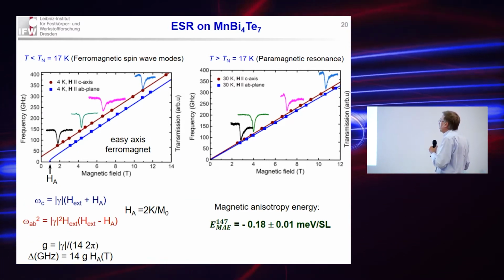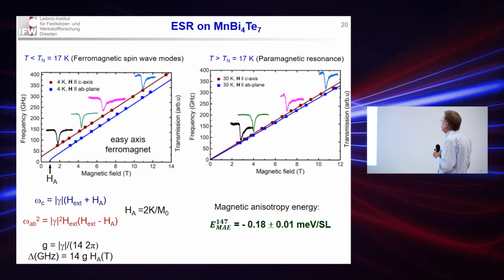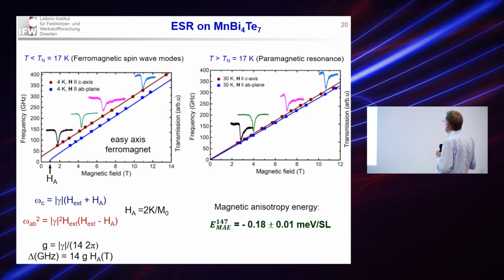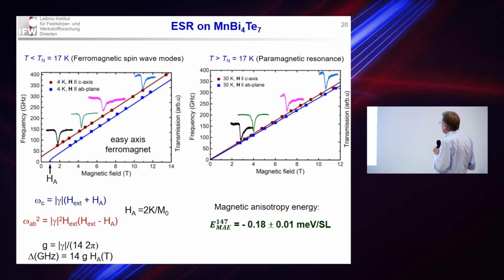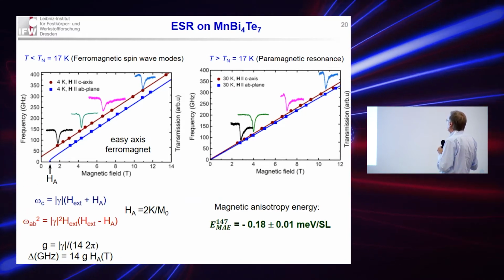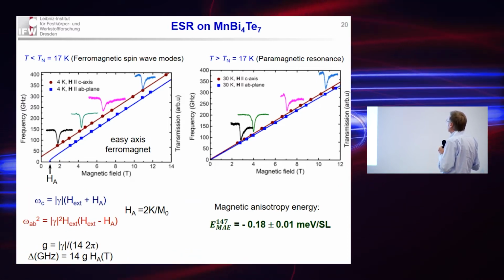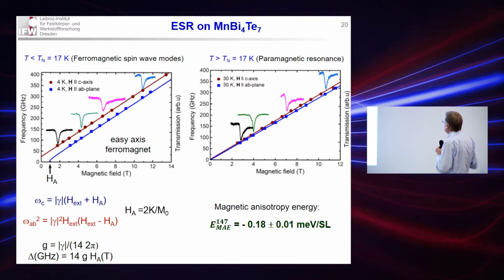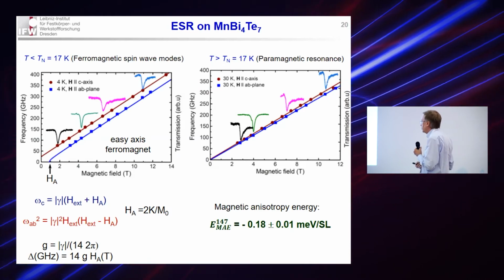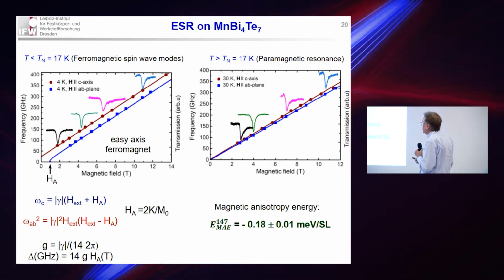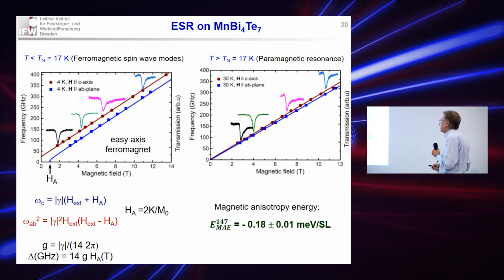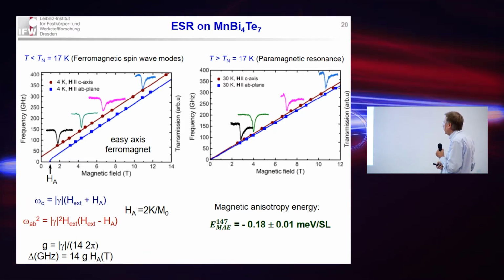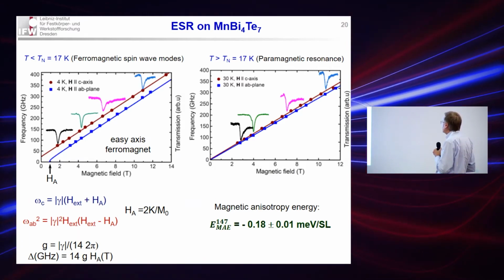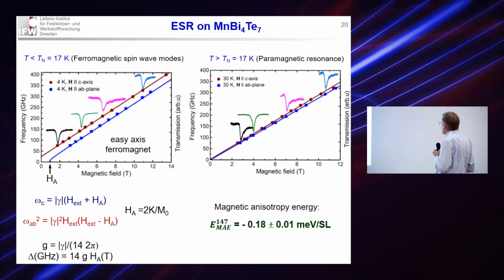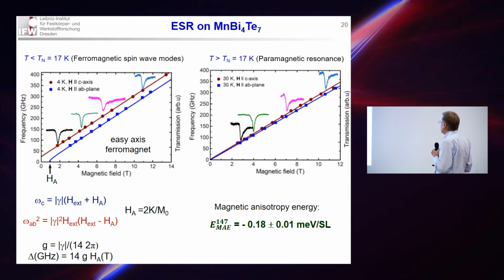So as soon as we heat the sample above the ordering temperature, the branches come closer together, they don't have a gap anymore, and this is a conventional paramagnetic resonant branch where the difference in the slope is given by the difference in the g factors. So we could analyze these excitations very easily in terms of the spin wave theory, and then we obtain quantitatively the magnetic anisotropy energy.